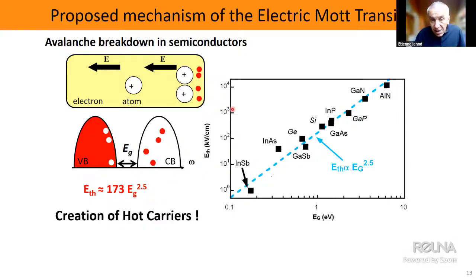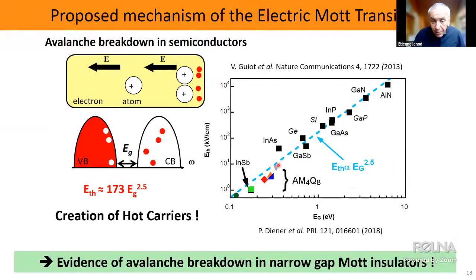And this is the evolution of the threshold field as a function of the gap in these semiconductors. It's a log-log scale, so you see that this power law corresponds to a straight line in blue. And the points in these classical semiconductors reproduce what happens in this family of systems. Here I add a data point, and it matched nicely on this curve of classical semiconductors. So this is some kind of evidence that probably an avalanche breakdown is also at the origin of what we observe in systems which are narrow-gap Mott insulators.